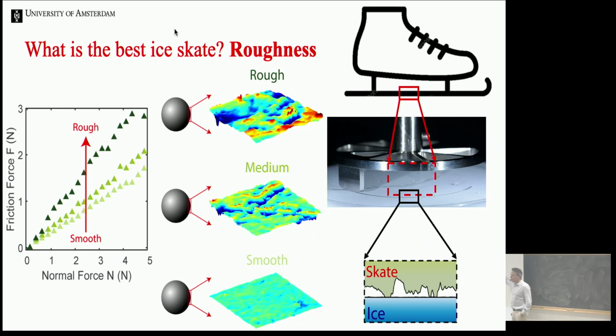So, if you buy a new pair of ice skates, they're actually very nicely polished. And this turns out to be very important because the roughness of the surfaces, as I just told you, also does something. And what the roughness does is, if you are very rough, you have a smaller contact surface, and that means that you have a higher pressure and you get more plowing.